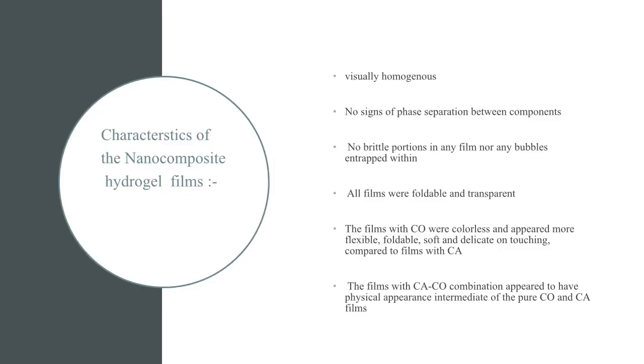Now here we have the characteristics of the nanocomposite hydrogel films. They were visually homogeneous. There was no sign of phase separation between components, also no brittle portions in any film, nor any bubble entrapped within. All the films were foldable and transparent, and the films with clove oil were colorless and appeared more flexible, foldable, soft and delicate on touching compared to films with cinnamaldehyde. The films with cinnamaldehyde and clove oil combination appeared to have a physical appearance intermediate of the pure clove oil and cinnamaldehyde films. And we would carry out later a thorough investigation in terms of structure elucidation, morphology, hydrophobicity, thermal stability, and other analysis as planned at the beginning of the research.